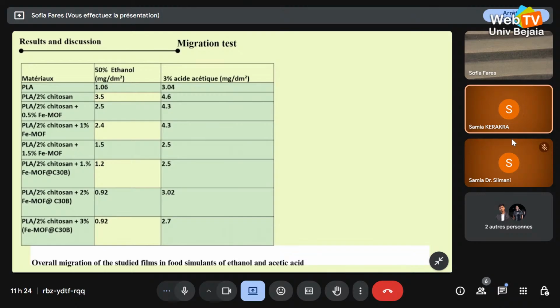The migration test, as we can see in this table, all films show migration values below 10, meeting the EU regulation, and adding 2% chitosan increases the migration due to the hydrophilic nature and OH and NH2 groups, which favor diffusion. And the addition of clay and the MOF reduces migrations thanks to their barrier effects, creating tortuous diffusion paths that slow molecule passage. These composites balance biodegradability and barrier safety, making them suitable for food packaging application.